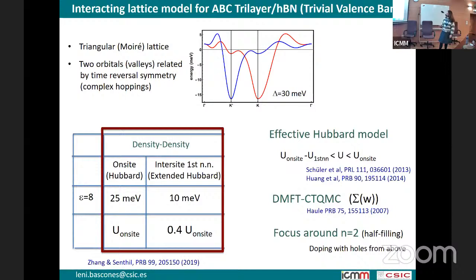And I'm going to study the system with dynamical mean field theory, studied with the continuous-time quantum Monte Carlo approach, as implemented in the Rutgers code. What we can look at with this dynamical mean field theory is that it is able to address Mott physics, and it does so in a way in which the self-energy depends on frequency but does not depend on k. So in fact, essentially local interactions means this k-independent part of the self-energy.